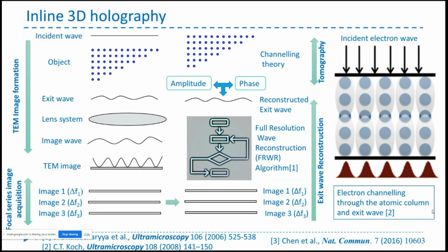Think this way: if it goes through a homogeneous sample, where the level of homogeneity is below the wavelength of the electron beam, which is in picometers, then you will see no change in the phase of the exit wave. Because it's a thin sample, the amplitude doesn't change much. So we should not worry about amplitude, mainly phase.